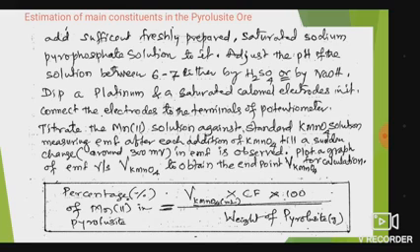Titrate the Mn(II) solution against the standard KMnO4 solution, measuring EMF after each addition of KMnO4 till a sudden change of around 300 millivolt in EMF is observed. Plot a graph of EMF versus volume of KMnO4 to obtain the endpoint, that is the volume of KMnO4 for the calculation.